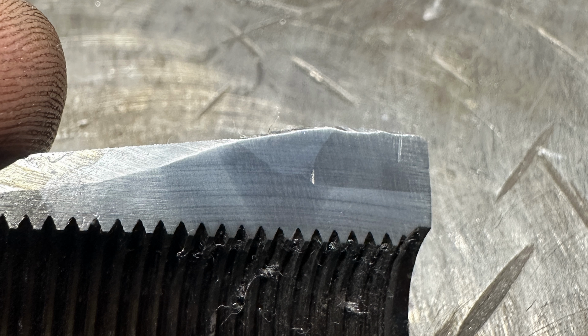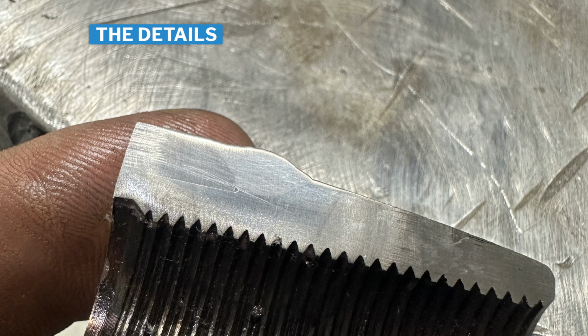And could it have more fusion? Yes. We would have had to run a bigger gap, and the problem with the bigger gap is the more heat input and the deeper the penetration gets closer to those threads, now you're going to have to chase the threads. And honestly, the strength that this needs, based on the fact it's welded fully all the way around the tube, I don't know how much more you're really going to gain. If it's of a concern where you want maximal penetration all the way through, then you're going to have to run a bigger gap.